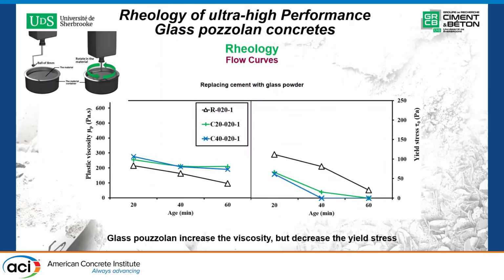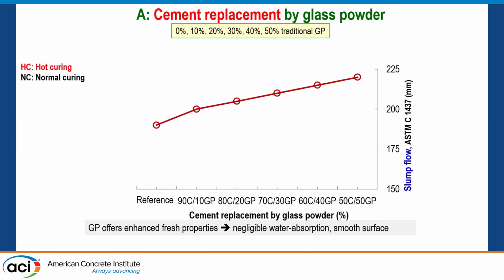So this is just a work that recently was redone by Arilas Begrish, and for the specialists in rheology, you know that it's very difficult to measure the rheology of UHPC, but he used this ball system with which we can measure the rheology. So the findings are mainly that yes, the glass pozzolan increases the viscosity, but this material is just flowing, doesn't stop to flow. So the yield stress is very good. So it's just continuously viscous but continuously flowing.